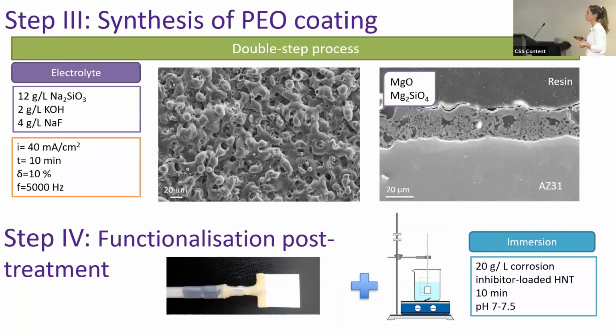It presents a porous and craterized morphology. And here we can see in the cross-section that it's composed of a 3-layered structure comprising an inner barrier layer, an intermediate layer with variable porosity, and an outer layer with quite big folds. And it's this porosity that is going to act as reservoirs for my corrosion inhibitors.